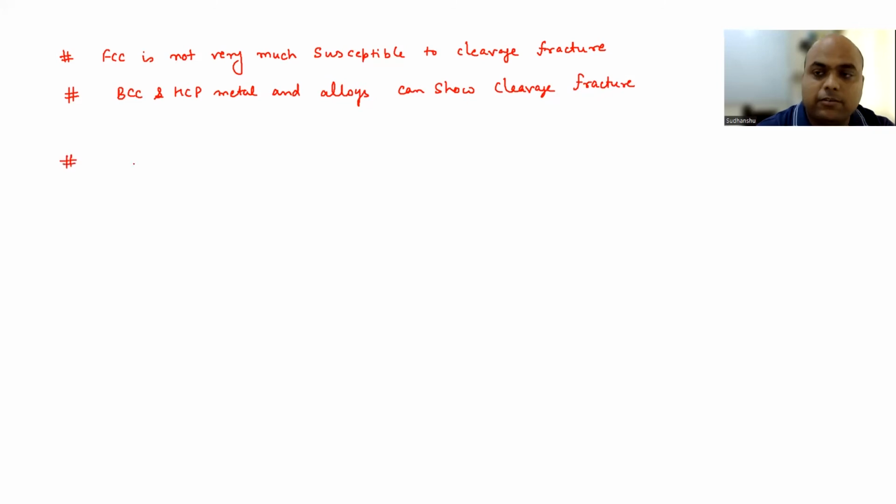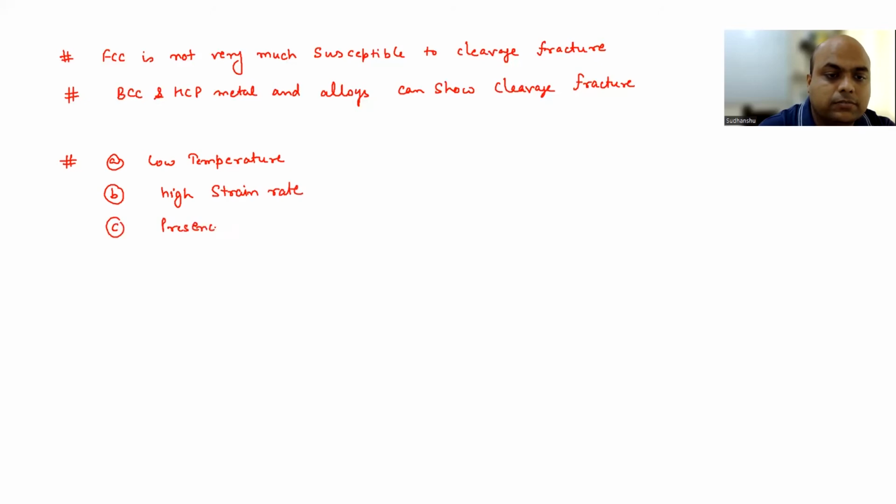So there are a few conditions. The first is low temperature. Second is high strain rate. Third is presence of notch, crack. Fourth is say corrosion.